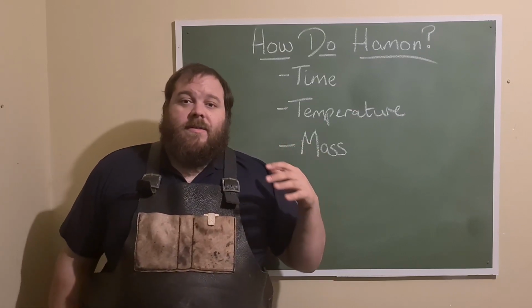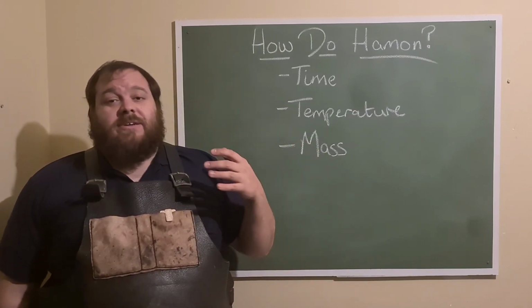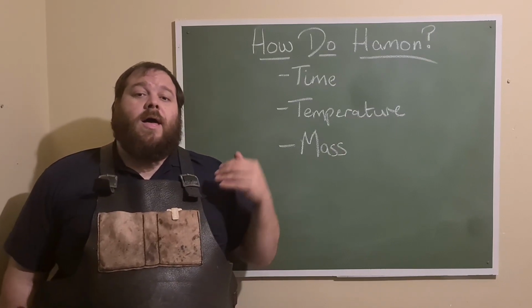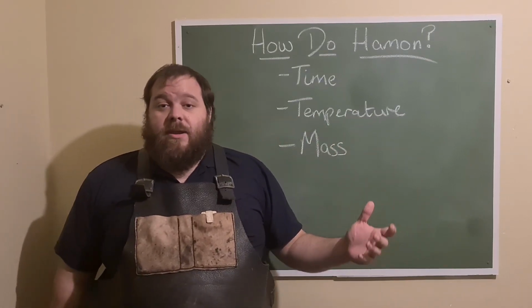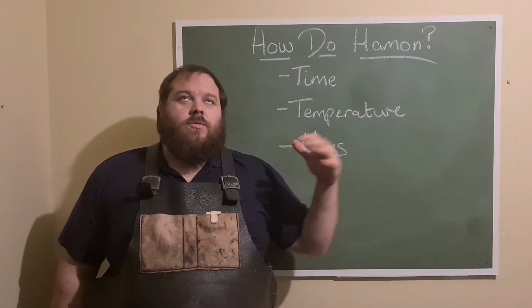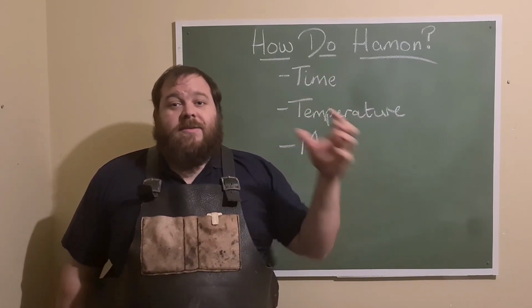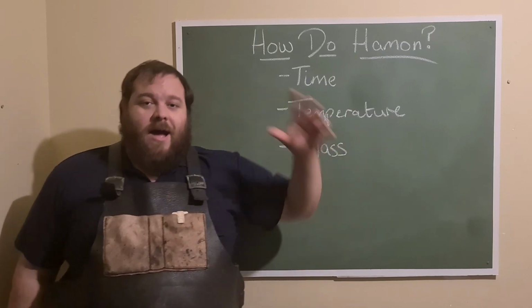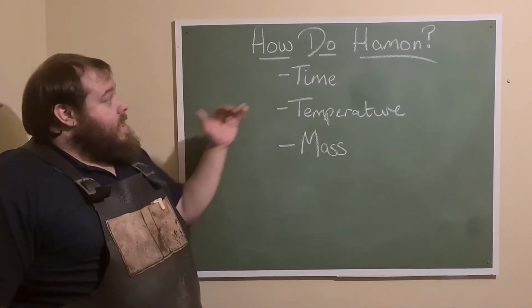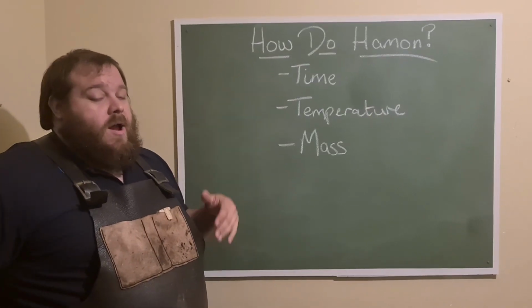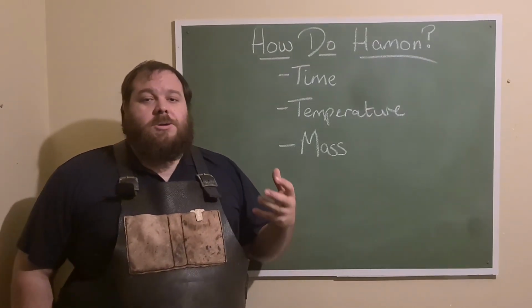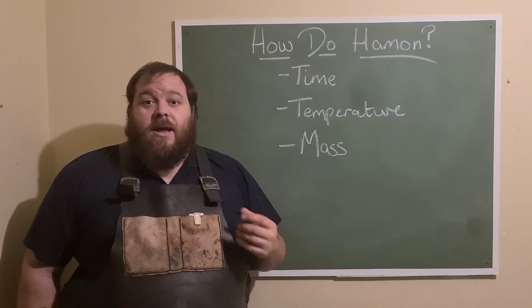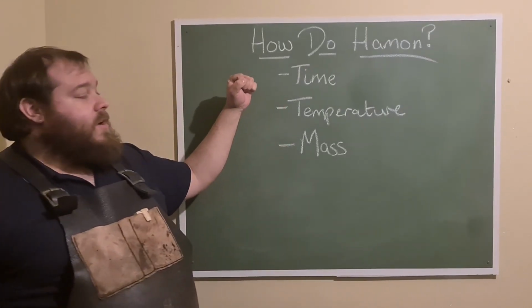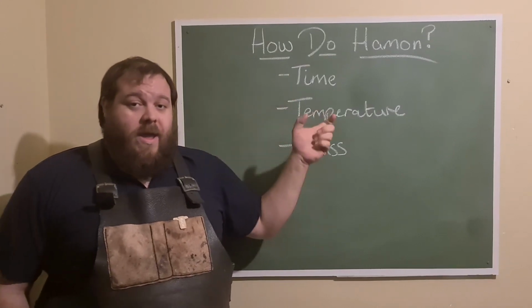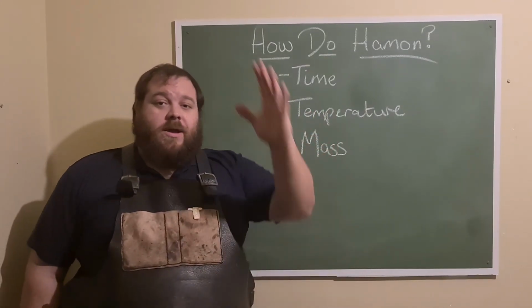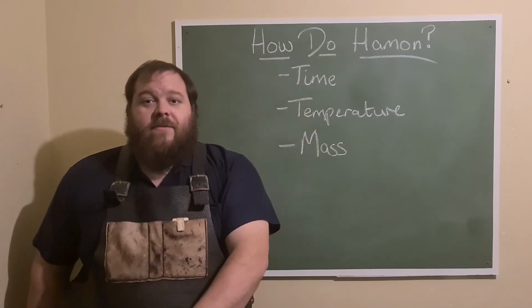With shallow hardening steels, they do not like to soak at temperature. This is why stainlesses are really bad for Hamon, because they require 5-minute, 15-minute, 20-minute periods at temperature to dissolve the carbon and chromium into the mix so that they can then harden all the way through. The other thing is that stainlesses require a relatively slow quench, air quenching, plate quenching, that kind of thing. In the case of Hamon, you want a very quick quench because you want to go very quickly up to temperature and then very quickly away from temperature.